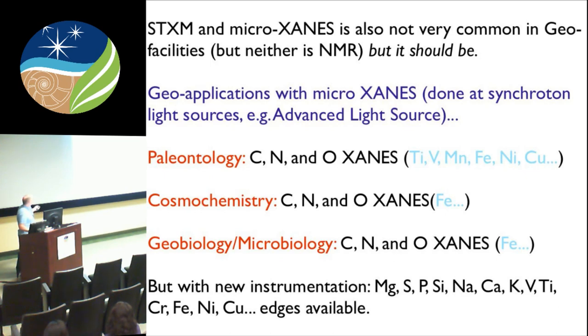And these are some of the applications that we've done using micro-XANES. In this case, the Advanced Light Source applied to paleontology, cosmochemistry, geobiology, and microbiology. There are some new variations on the theme. Where we started out with carbon, nitrogen, and oxygen, we could easily do iron and titanium and vanadium and manganese. But now with the new variations, we can do nickel and copper, we can do magnesium, sulfur, phosphorus, sodium, calcium. The whole periodic table is opening up.